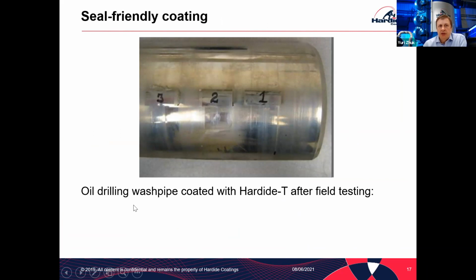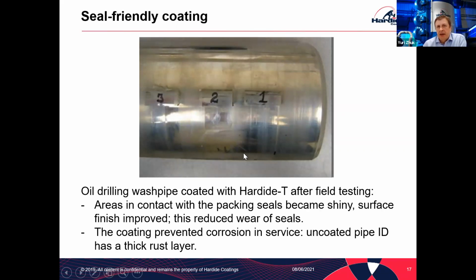Another interesting property is the coating is seal friendly. So in one application, the customer tested an oil drilling wash pipe. And what we saw after some usage was that the coating actually got more polished where it was in contact with the packing, with the seals. And as a result, the seals did not wear. So the seals and the wash tube lasted longer, did not leak, did not require replacement, and allowed continued operation for longer. And at the same time, the coating protected the wash pipe against corrosion.